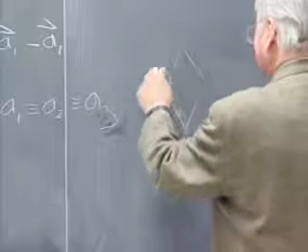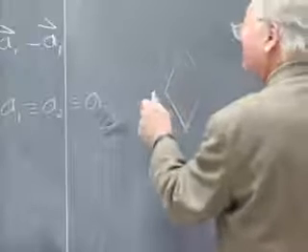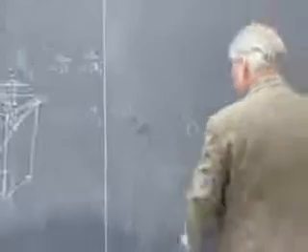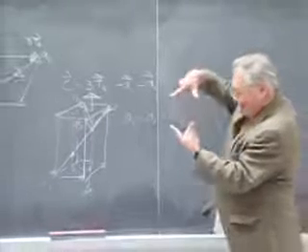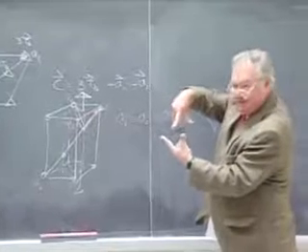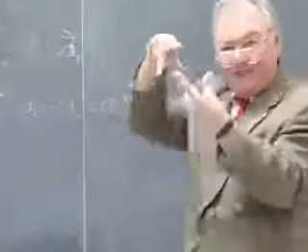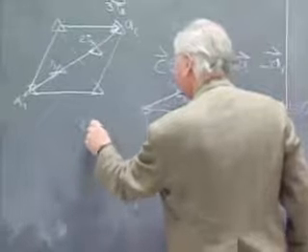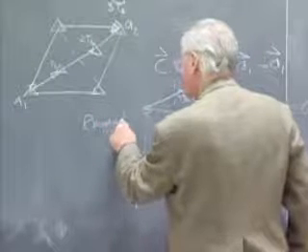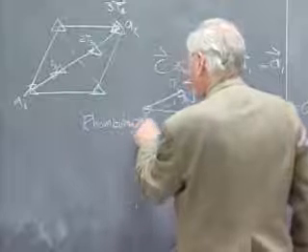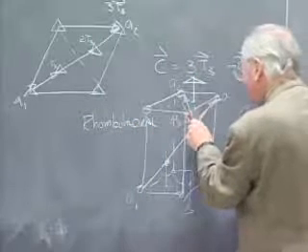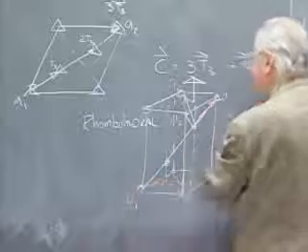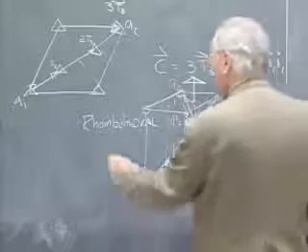And as I say, I always get in trouble when I try to draw it. It's got 3 translations like this and 3 translations skewed by 60 degrees sitting on top. Everybody can see that's a rhombohedron, can't you? Say yes, be nice. So this is another primitive cell that's a choice for this triple cell, and this consequently gives its name to this lattice. This is called the rhombohedral lattice, regardless of whether you pick the primitive cell in the shape of the rhombohedron or this peculiar double body-centered cell. So this is a rhombohedral lattice.